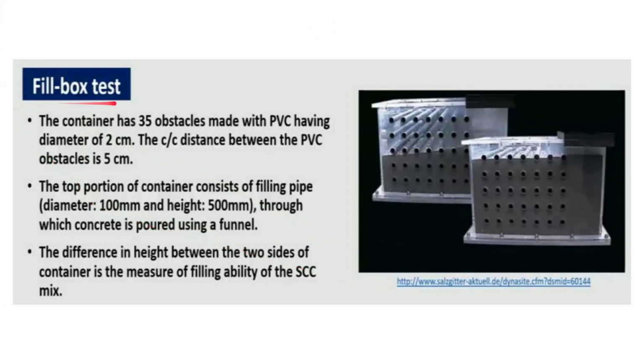And apart from that, there is one more test which is called the fill-box test, okay. So the fill-box is basically a container which has 35 obstacles made with PVC, having a diameter of 2 centimeter. The center to center distance between the PVC obstacles is 5 centimeter. The top portion of the container consists of a filling pipe, diameter 100 mm and height 500 mm, through which concrete is poured using a funnel.